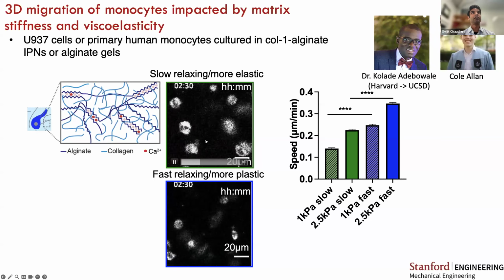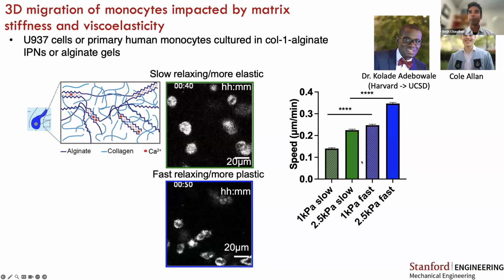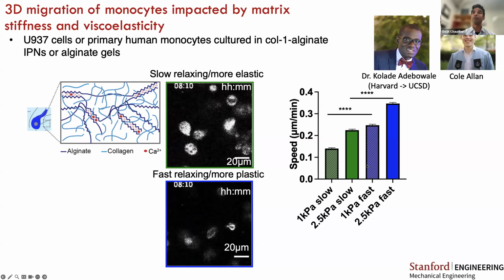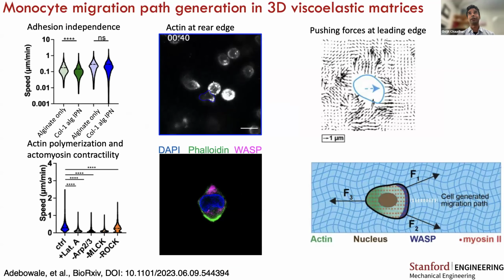So we see in these videos that some of these monocytes are migrating quite robustly. We can track the migration, and we see that both increased stiffness and faster relaxation enhance the migration of these monocytes. So we've done some mechanistic studies to try to understand the mechanisms mediating this monocyte migration. What we see is that the monocytes migrate independent of adhesion. If we remove the collagen and we look at migration in alginate alone, the speed is essentially the same. So they don't need integrin binding ligands to migrate, which is something that's very common and typically observed in immune cells. If we inhibit actin polymerization and actin-myosin contractility, that inhibits migration.